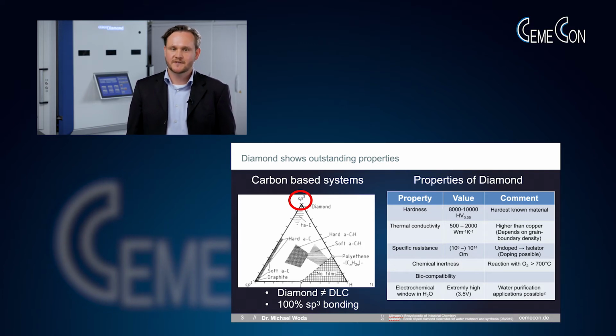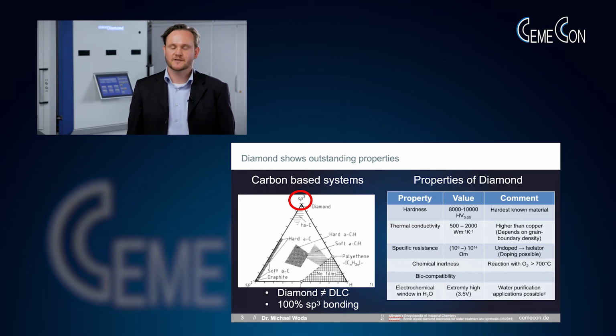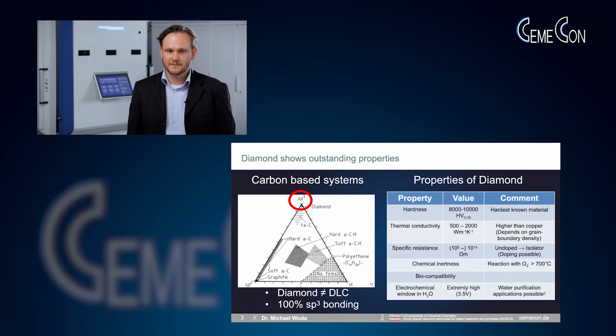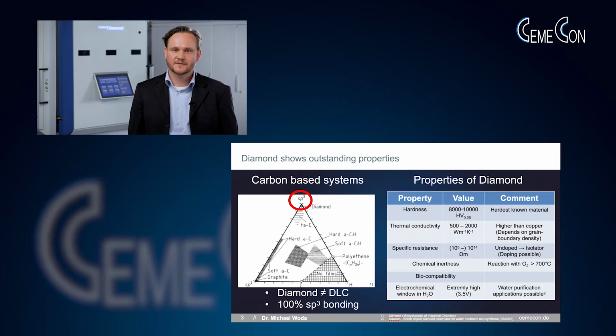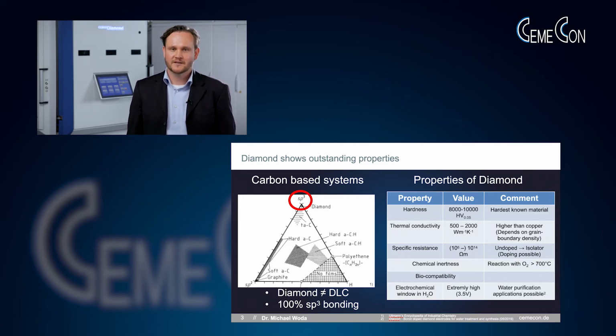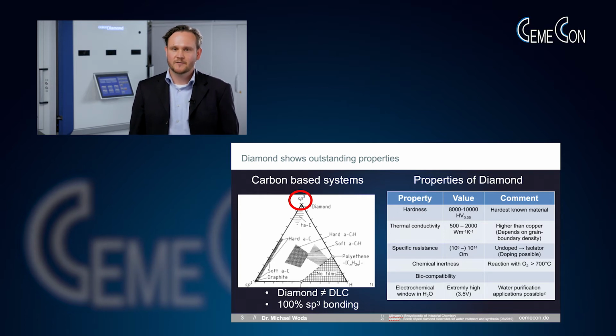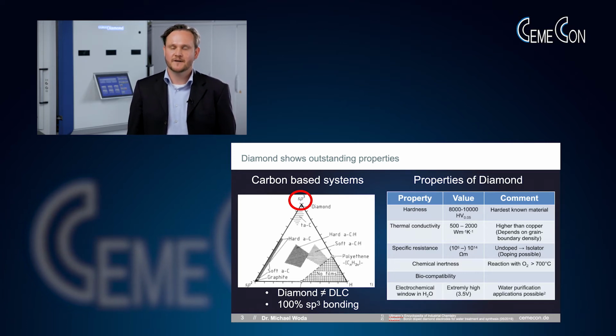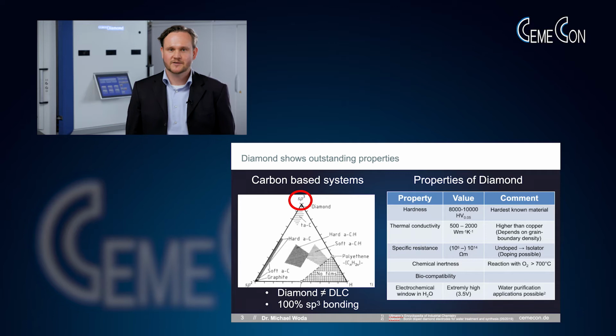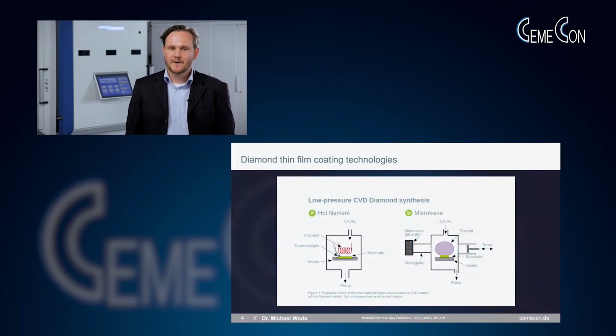Apparently, diamond is the hardest known material with a 10,000 Vickers hardness. It shows a very high thermal conductivity, which is able to compete with metals, although it is an electrical insulator with a large optical band gap. However, it is also possible to produce conductive diamond coatings when the application demands this. Diamond is chemically inert. Diamond is biocompatible due to its carbonic nature, and diamond has a very high electrochemical window in aqueous environment, which allows water purification processes, just to give you an example for an application apart from the cutting tool business. We might ask now how our diamond coatings are produced.